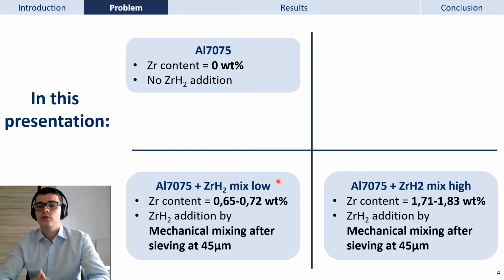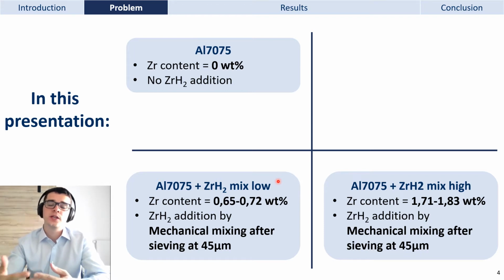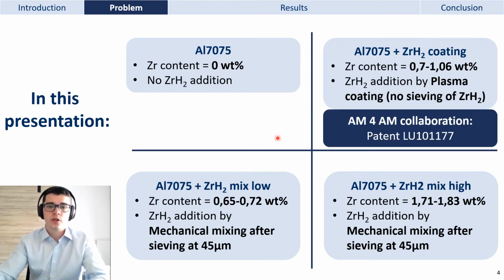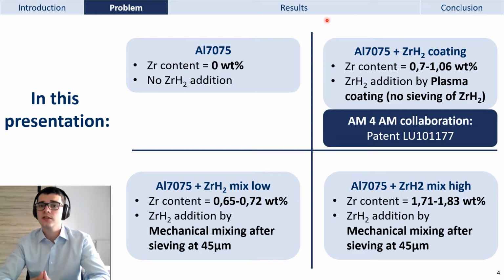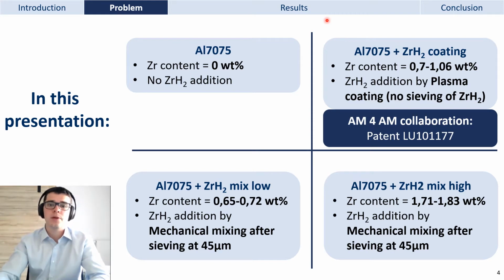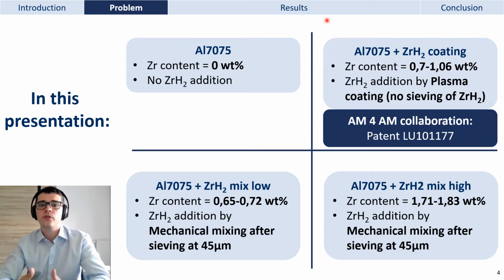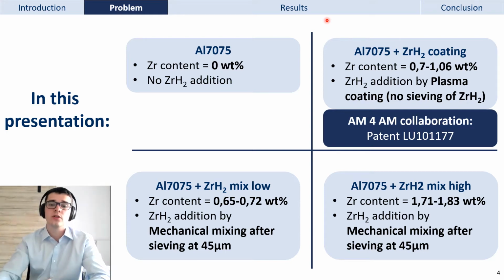the samples. The zirconium hydride powder was sieved at 45 microns before being mechanically mixed in order to remove the biggest particles. For the fourth alloy, another way of adding the zirconium hydrides to the aluminum 7075 powder is used. Indeed, zirconium hydride is added thanks to AM4AM's patented technology, which consists in the grafting of ceramic particles on the surface of aluminum powder by means of an atmospheric cold plasma discharge. We are collaborating with this startup to fully characterize the impact of this innovative process on the final properties of the part since it is still under development.